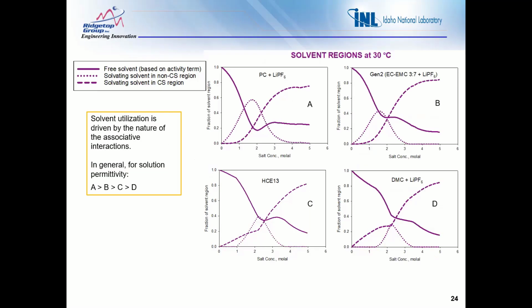Okay, next slide. Okay, I'm going to step through these real quickly. So this is a summary of how the solvent starts to be partitioned or has different regions of existence within electrolytes as you add salt to different electrolyte choices. So as we go A, B, C, D, the permittivity, or dielectric constant, starts to decrease across those 4 choices. So A is the highest, D is the lowest permittivity. The solid line here is the free solvent that remains. In other words, it's not engaged in solvation of anything.